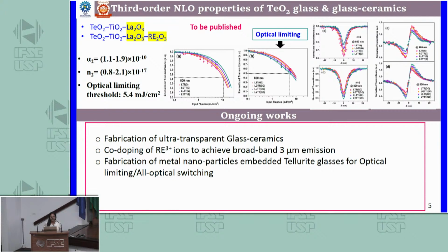And currently, I am also working on third order nonlinear optical properties of tellurite glass ceramics, which exhibit at least 10^3 times higher nonlinear absorption coefficient compared to commercial nonlinear optical materials or fused silica, and can be used as an optical limiting material with a low radiation threshold.